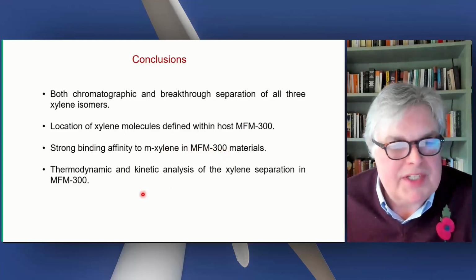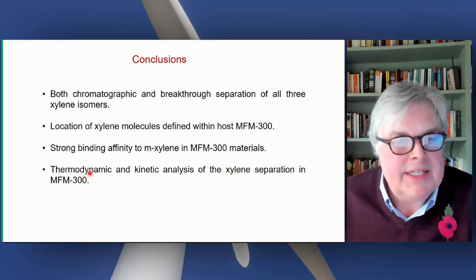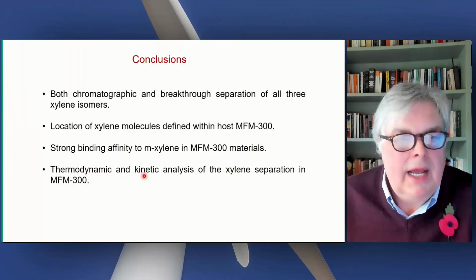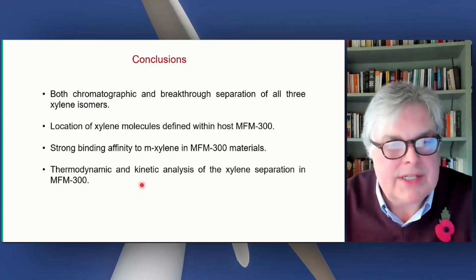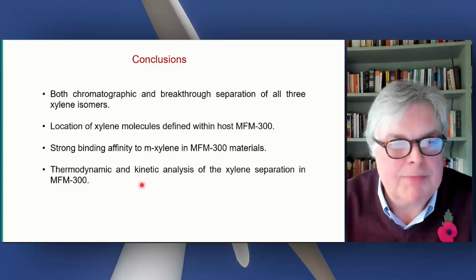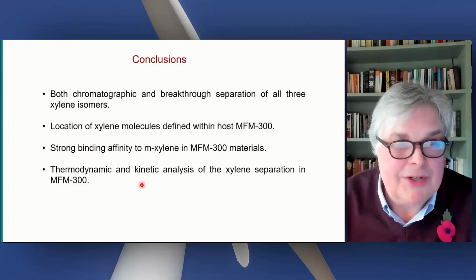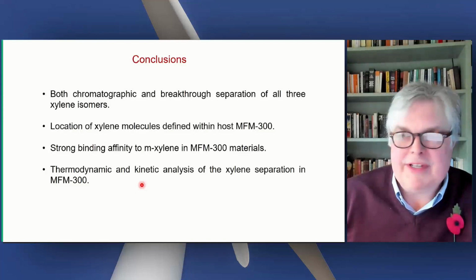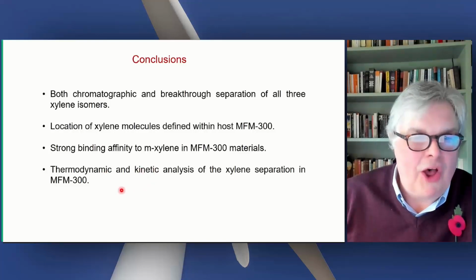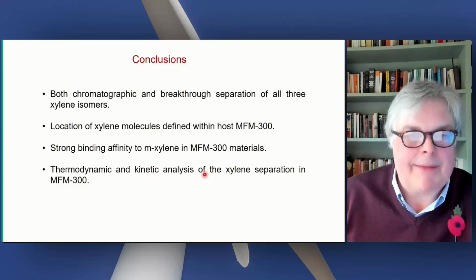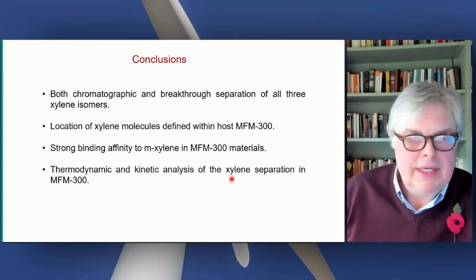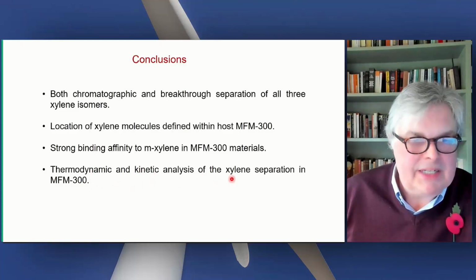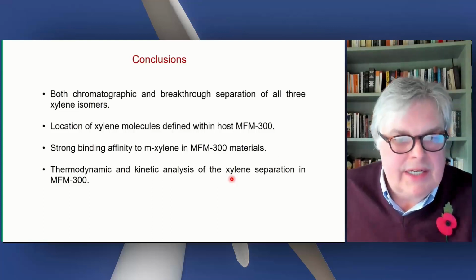And what I've, of course, skated over completely is the whole issue of thermodynamic versus kinetic separations. Some of these xylenes actually enter the pores much more slowly than into other MOF materials. So there is a whole analysis here of thermodynamic and kinetic separations that complicates the issue, and actually needs to be very closely considered and understood.